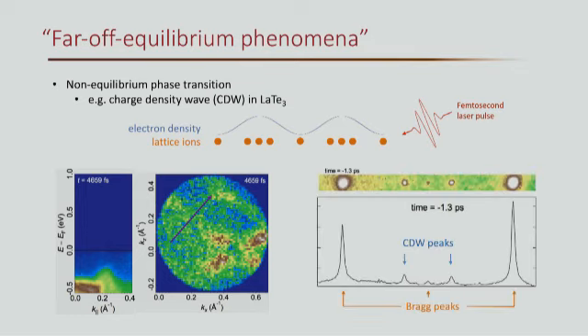And of course, a second probe we can use is to look at how the lattice ions respond to this ultrafast laser pulse. So here we're looking at an electron diffraction pattern. In a normal crystal, we can see Bragg peaks, but when the system is in a CDW state, you can also see superlattice peaks due to the superlattice formation. So these two little dots indicated here are the superlattice peaks. And as the pump arrives, you can see the suppression of the peak. And then soon after, the peak recovers.